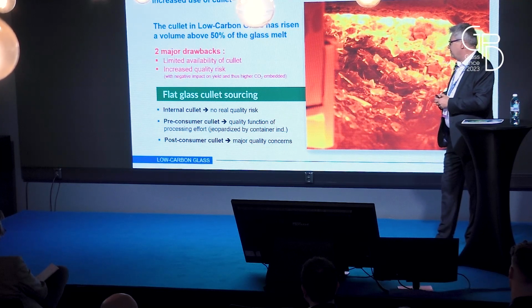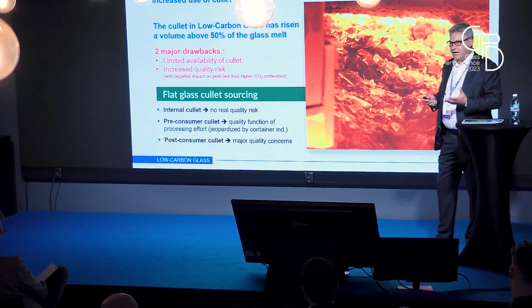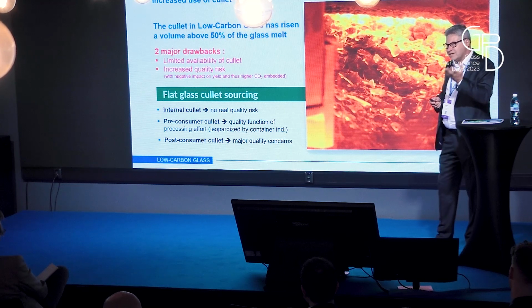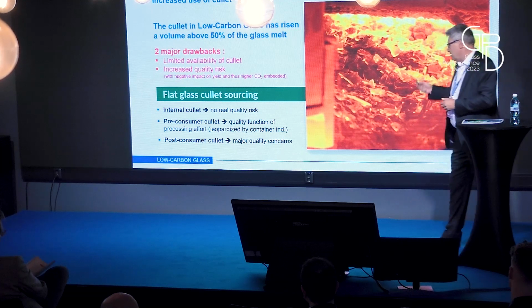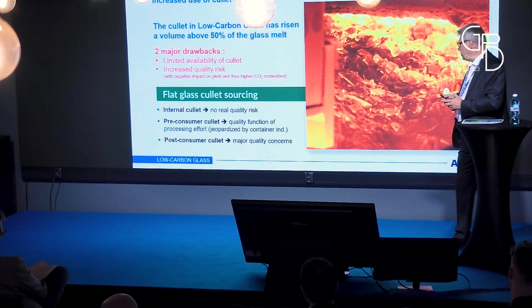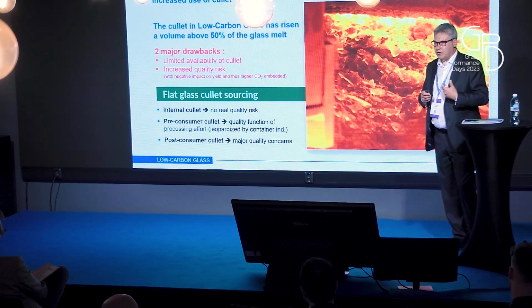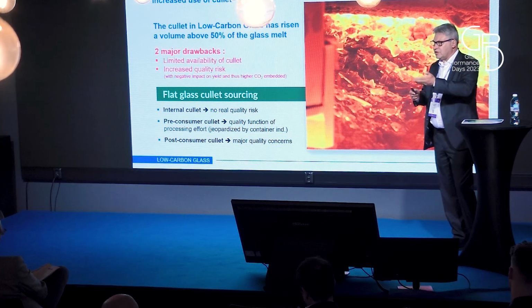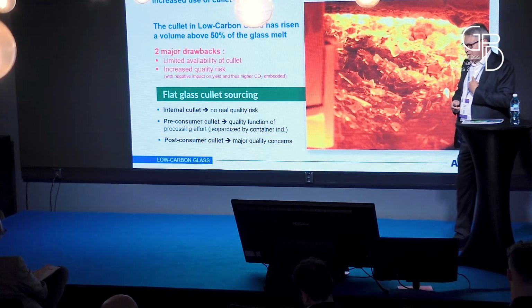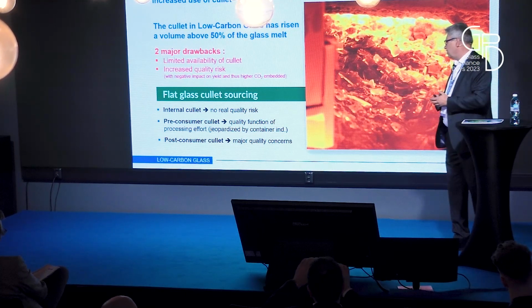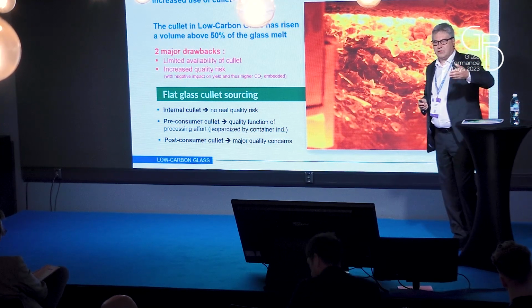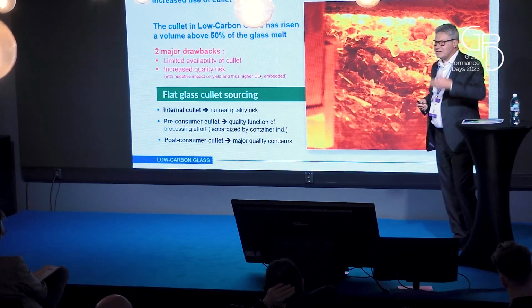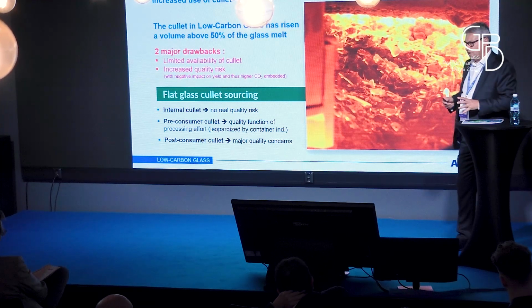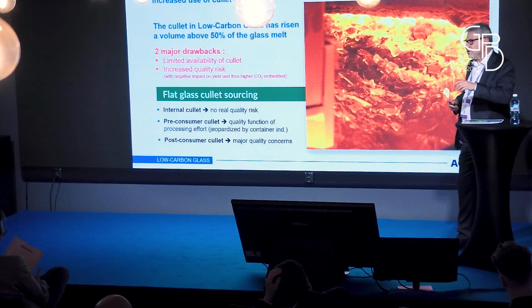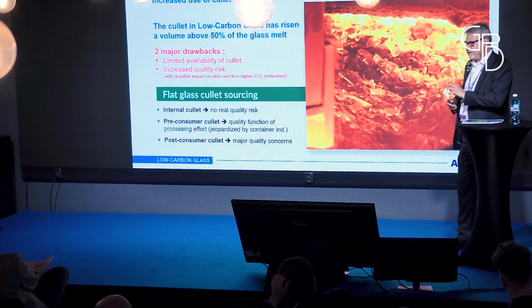So typically, 50% of the total volume in the furnace is cullet. 50% is a minimum. We go to 60, 65, depending on the thickness of the glass. Of course, with internal cullet, there is no real quality issue. We use more and more pre-consumer cullet. It means glass that is coming from our subsidiaries. So it's typically the cutting losses when you make windows from Jumbo and so on, from AGC, but also from our customers, and we collect all this glass. The post-consumer cullet is the glass that has been put into double glazing on a building, and it comes back after several years. This part has more quality concerns, and it's a real challenge to control it, to clean it, and so on. At this moment, to be honest, we do not use so much of this part.